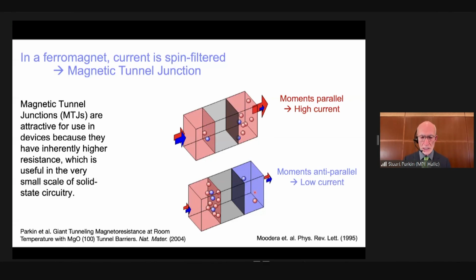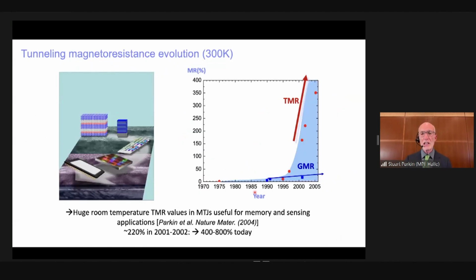And this is something that I showed in a paper I published in Nature Materials in 2004. And this was a breakthrough that made possible the use of these tunneling junction devices as spin valve sensors based on spin-dependent tunneling. And this enabled, again, further increases in the storage capacity in a magnetic disk drive. This is shown here, how the tunneling magnetoresistance, which I just discussed, versus the spin valve magnetoresistance evolved as a function of time. And you can see the spin valve magnetoresistance at room temperature is relatively small, a few tens of percent, but the tunneling magnetoresistance can be hundreds of percent.